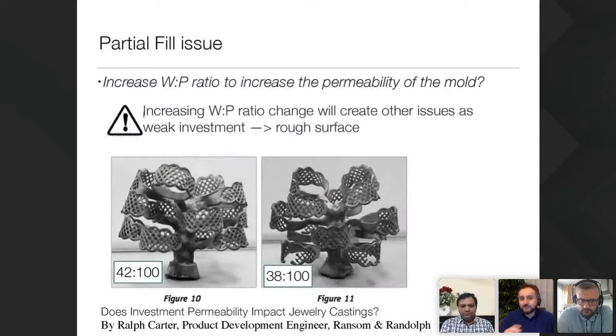Yes. Another suggestion that I've seen in one of those papers, and it's not very common in the market, is about the permeability of the investment. A way to increase that is to put more water. What they did is they put a lot of water. The ratio is 42 to 100, and by doing that, they could increase the permeability of the investment by 30%. So it becomes more like a sponge, which means your vacuum would work better.